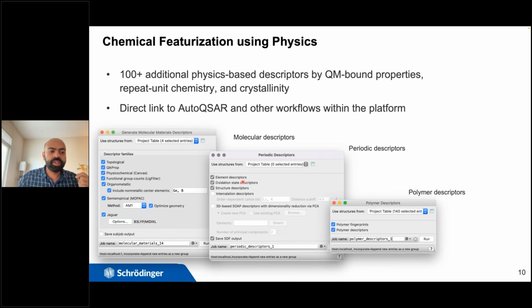For example, these element descriptors and oxidation state descriptors are actually based on the Matminer descriptor approach, where we take the stoichiometry of an inorganic solid and calculate the stoichiometric descriptors. And we also have a 3D descriptor approach called the smooth overlap of atomic positions, where we would take a molecule or periodic solid, and using the smooth overlap of atomic positions method, which generates a rotationally and translationally invariant basis set for the atomic environments, we can actually characterize the 3D structures of these molecules and periodic systems. And once these descriptors are generated, we can add them as additional descriptors to AutoQSAR or to DeepAutoQSAR to improve the performance of the model.